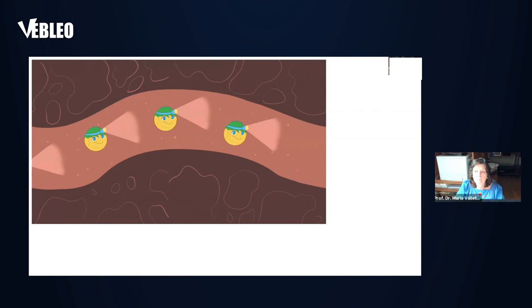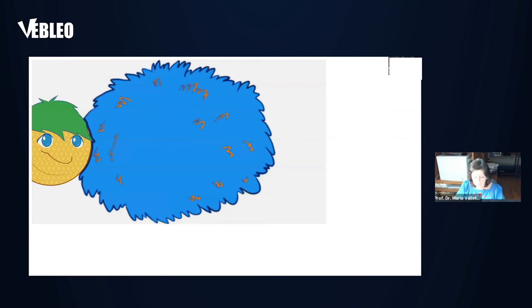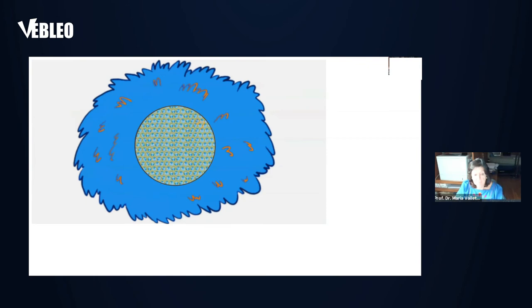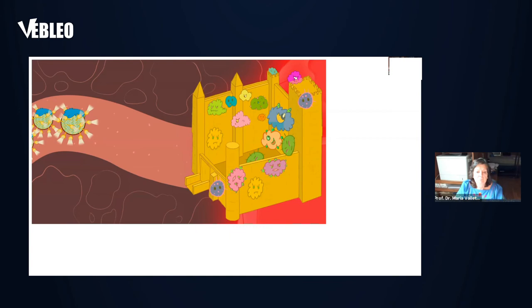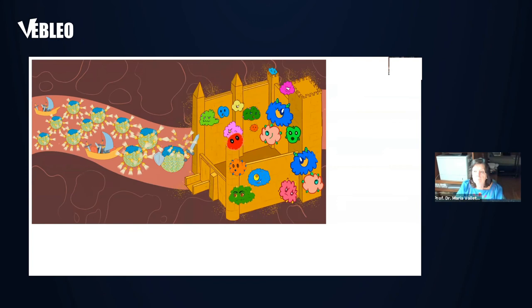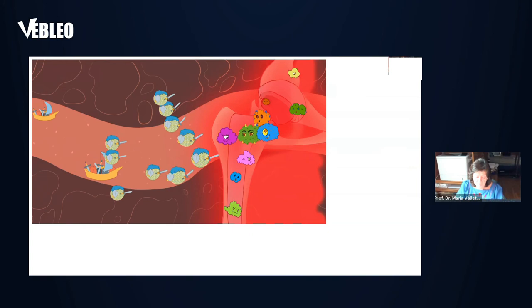In the bloodstream, they can direct them to the objective, the infected bone. Once there, if the biofilm is not yet formed, the destruction strategy acts on the bacteria themselves, penetrating them. To achieve this, small amine molecules or macromolecules such as dendrimers and cationic polypeptides can be used. In this way, the particles are internalized inside the bacteria and kill them. If the biofilm is already formed, a destruction mechanism must be put in place. To destroy the biofilm, antibiotics are incorporated into the pores of the mesoporous silica nanoparticles and lectins on their surface. Lectins are molecules that specifically recognize the mucopolysaccharides present in the biofilm. And when the nanoparticles reach it, they release the antibiotic, eliminating the infection.